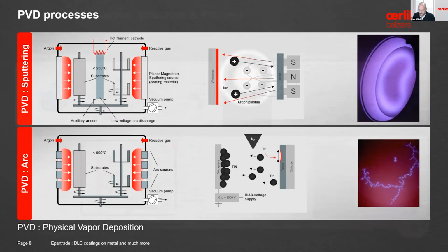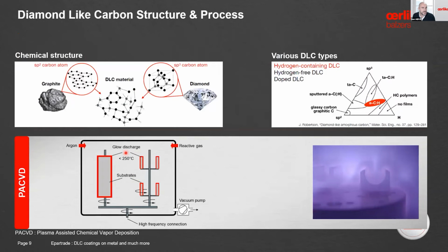The other process that we use to apply a now very well-known solution, called DLC coating, diamond-like carbon coating, uses a slightly different system. In this case, we will use only a gas environment to apply the DLC. And this is why the DLC very often is made at a lower temperature.